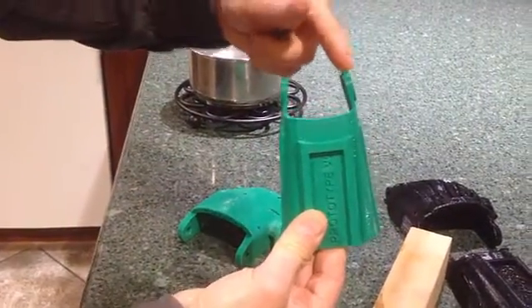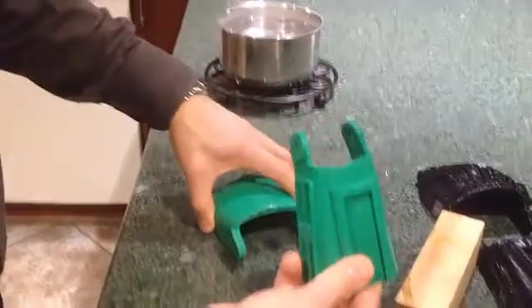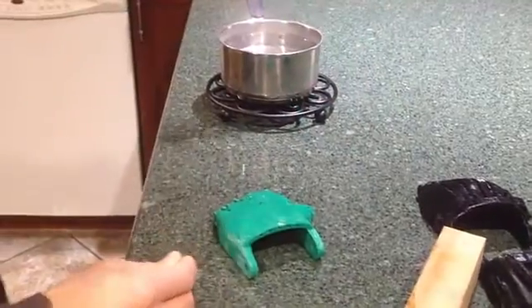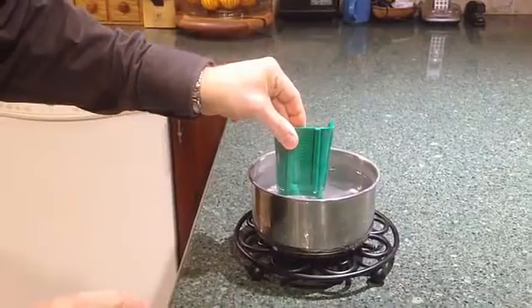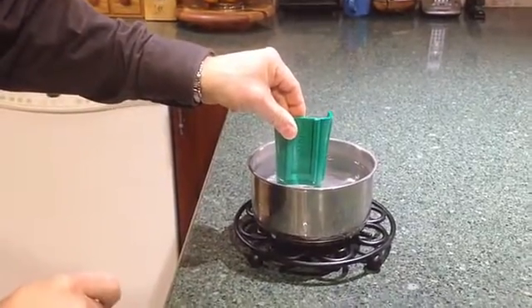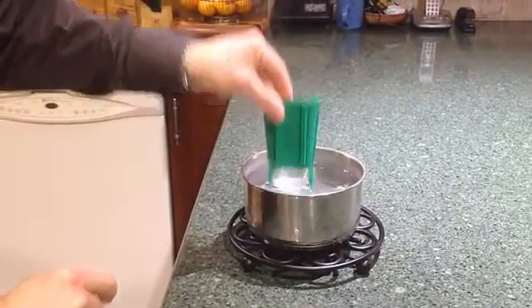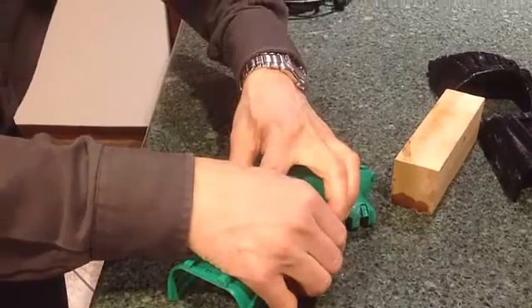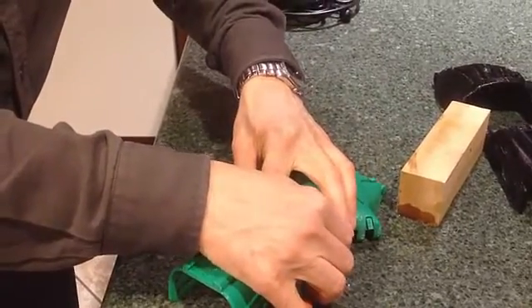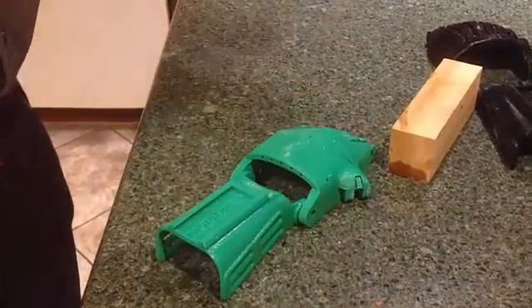If you look at the hinge mounts, they're going to be way undersized — that's not a problem. We're now going to go to the third step of forming, where I'm going to dip it again up to the end of the dovetail joint, again for about ten seconds. That's going to soften up the hinge so I can form it into the shape I want. Having the palm available is important here because I'm pushing the edge of the hinge up to the edge of the palm where it would mate, so I can hold it just long enough until it sets.